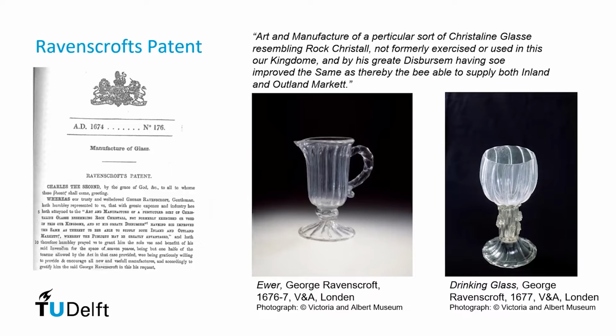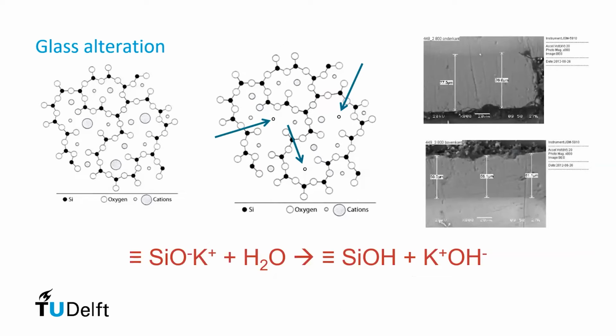Okay, next slide, please. So this is one of the two technical slides in my presentation, just to show you what is going on inside the glass during degradation. On the left is the simplified structure of glass where the silicon and oxygen form the backbone. So that's the black dots and the open white dots. And in between are cations. And these cations are added as the network modifiers. And they are somewhat mobile within the glass network, meaning that they can also be extracted from the glass network.